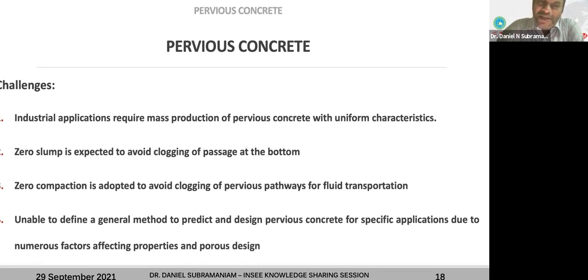One of the biggest problems that I find is the uniformity, because it's a porous structure. Every time you do a mix, if you don't have zero compaction or slump, you are going to end up with a different arrangement of binder-coated aggregates. You don't have fines, so you don't have a binder with fluid properties. Usually in conventional concrete, we speak of the concrete as a fluid. To be precise, it's a Bingham plastic fluid. So you give some yield stress, and after the yield stress, it's like a Newtonian fluid.